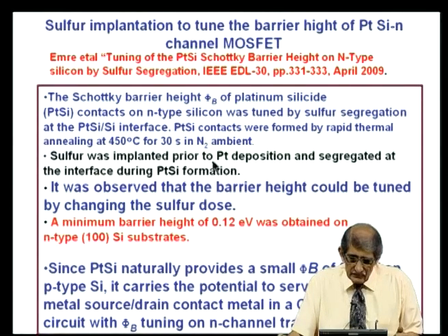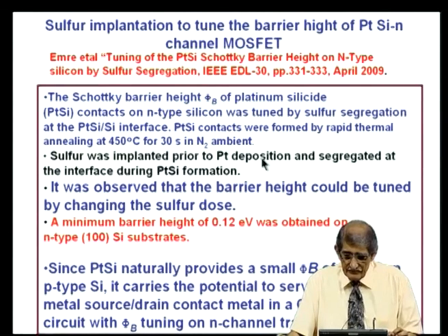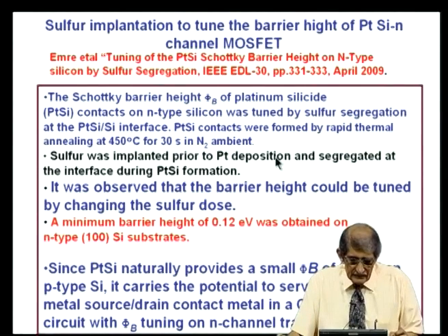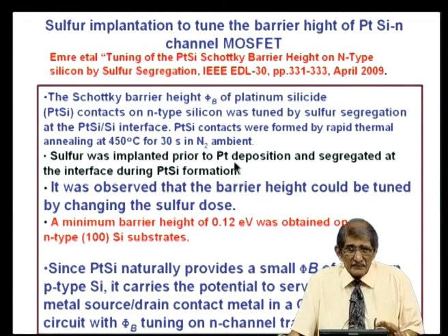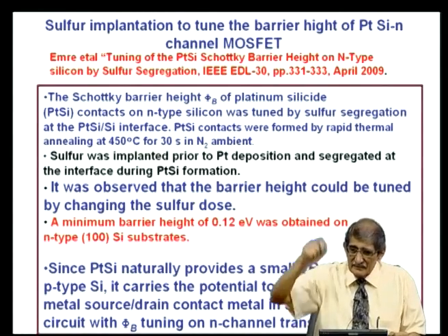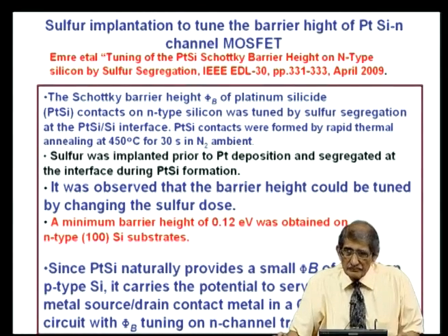Sulfur was implanted prior to platinum deposition. First implant sulfur, and segregate at the interface during platinum silicide formation. You implant sulfur, deposit platinum, anneal at 450 degree centigrade, rapid thermal annealing. What is rapid thermal annealing? Take the temperature very quickly, spike 30 seconds, bring it down.